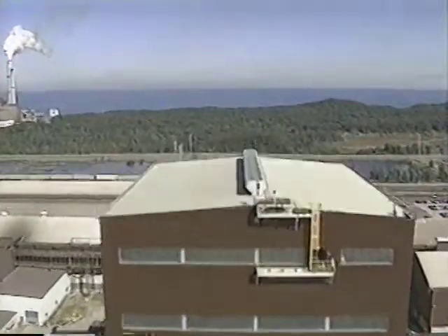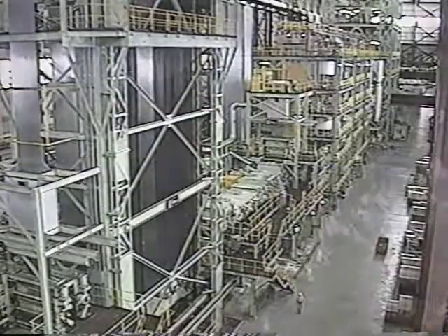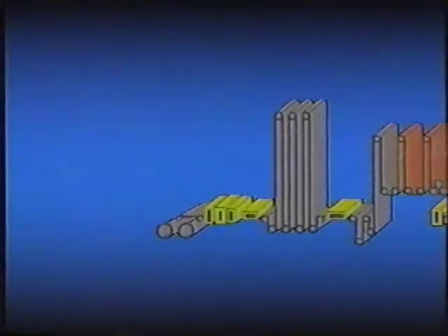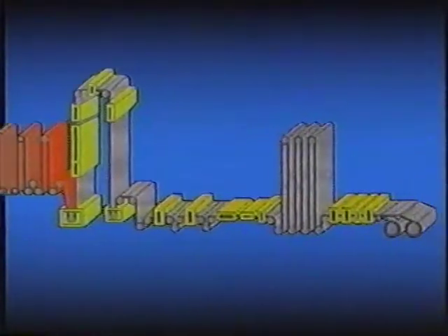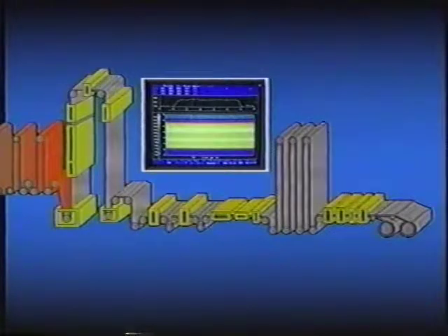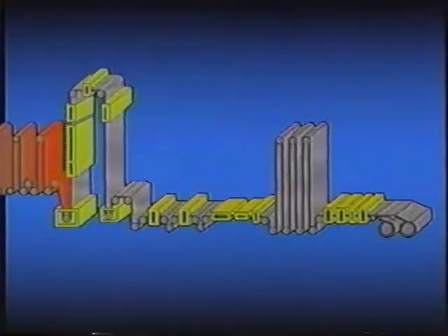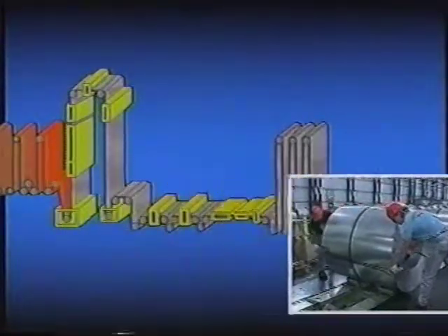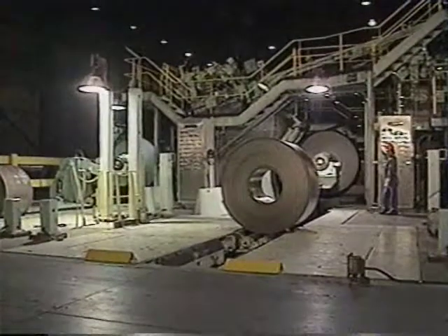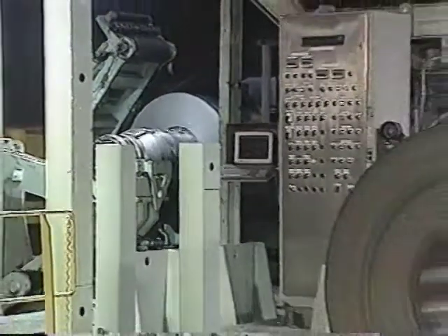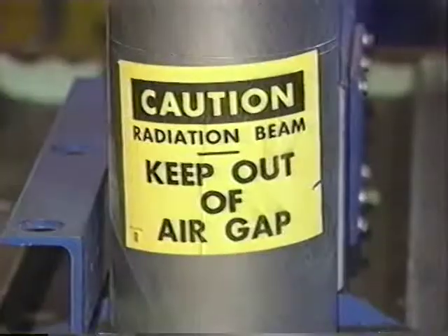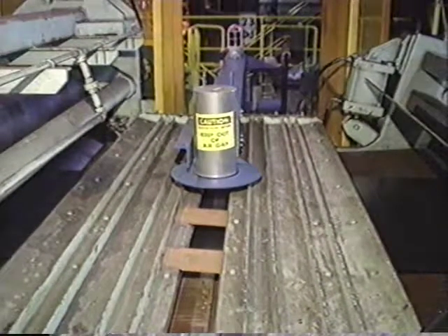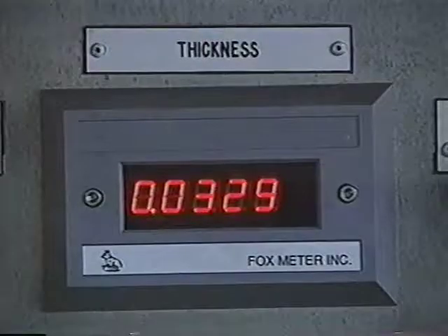Burns Harbor operates several coating lines to serve our automotive customers, and here is the newest one, our $200 million hot dip coating line for galvanized and galvannealed sheet products. From entry end to the shipping dock, this line is state-of-the-art, built in direct response to our automotive customers' needs. The line is computer-controlled, monitored for consistency and quality every inch of the way, and it's operated by a world-class team to give our customers a competitive edge. World-class coated sheet starts here with top-quality coils from our cold tandem mill. The hot dip line's dual entry reels provide a steady supply of steel. As steel moves into the line, X-ray thickness gauges and an entry end shear ensure that our customers receive sheet with uniform thickness.